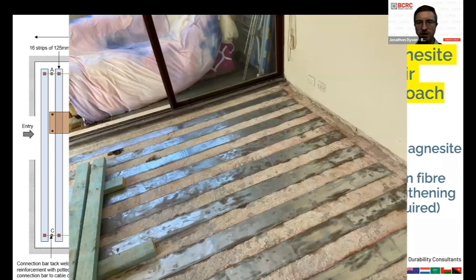And here's just one photo, one example of that ZAP magnesite system being installed in a magnesite affected building. And you can see, if you've got a sharp eye, you might notice that the magnesite's actually still in place in this case. Now, we don't usually recommend that as a good approach, because if you leave it in place, you're leaving a latent risk in place, essentially. However, it can be left in place if that is the desire of the owner.